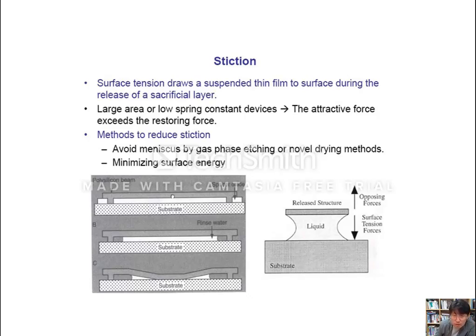Okay, during the removal of the sacrificial layer, what is the problem? Well, probably you know, to remove the oxide, you probably use a certain etchant to remove only the oxide, and then eventually it will be rinsed by water. The problem is, you expect to dry out this rinse water, right? The problem is that when this rinse water is evaporated in the oven, you may expect that it is all gone at the same time, but eventually it's not. What happens is that they evaporate from the edge, right? And then in the middle, the problem is, well, it's hard to say, but it could evaporate in the middle or at the edge.